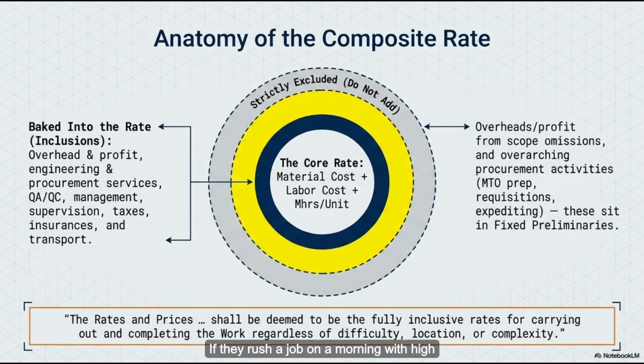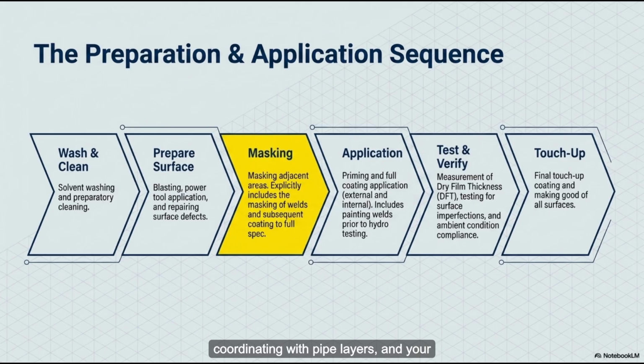If they rush a job on a morning with high humidity and the coating fails an adhesion test 2 weeks later, they pay for it all. Erecting the scaffolding, reblasting the steel down to bare metal, reapplying everything, all out of pocket. That's insane. You're managing hundreds of workers, coordinating with pipe layers, and your entire profit margin is tethered to a literal hygrometer. It really is.